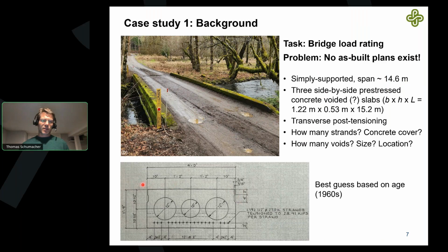The idea, or the guess, was that the cross sections look somewhat like this. They're prefabricated, pre-stressed concrete voided slabs. That's the best guess the engineer had. So basically, it has these big voids to save self-weight and make it lighter. But we didn't know. What we could do is measure the thickness, about 53 centimeters depth. And there were 3 of them side by side, and they were post-tensioned transversely to make a good shear connection.